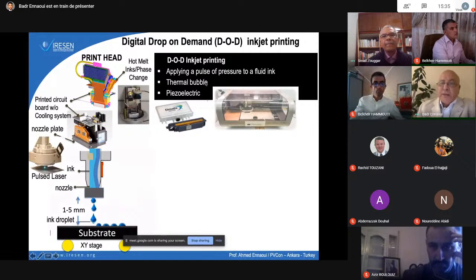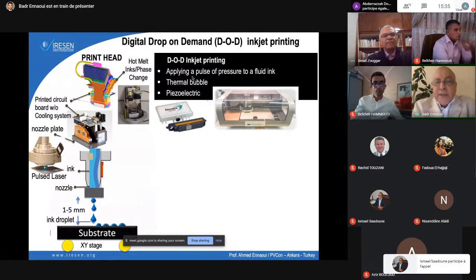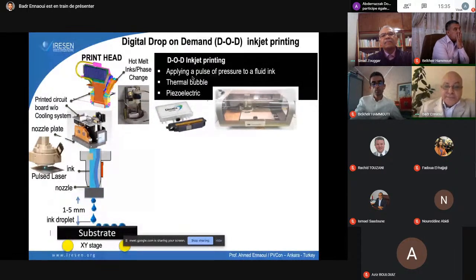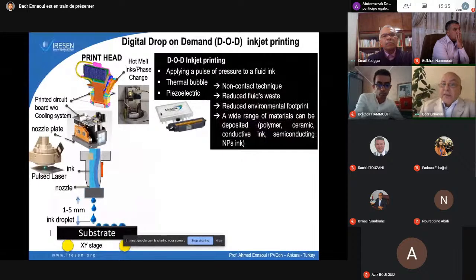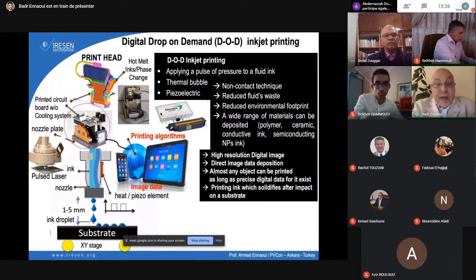So there are different ways to make a drop on a substrate by applying a pulse of pressure to a fluid ink, by thermal bubbles, by piezoelectric. So it's a non-contact technique. This means you make drop on demand. This means a very small amount, only what you need. So this means reduced fluid waste. So you reduce the environmental footprint, and you can prepare a wide range of materials like polymer, ceramic, semiconducting, nanoparticle, etc. And of course, you can use a printing algorithm, and you can print any image with high resolution, any image or any programmed materials.